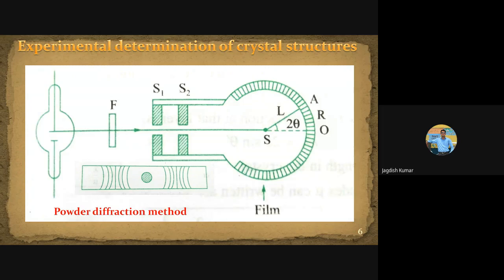Because whenever we mix certain reactant chemicals to create a crystal, we already decide the stoichiometric ratio of those elements according to which we expect our crystal to form. So we put all those values in the software, and then we generate a rough X-ray diffraction pattern, the calculated one, and the software compares the two.